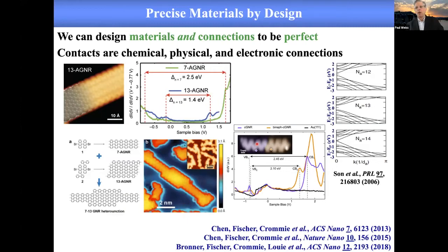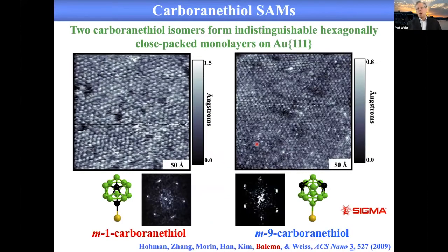Okay, going back to the self-assembled monolayers, those had all kinds of problems because the molecules out of which we assembled them were not rigid structurally. They could conformationally relax, they tilted, and so forth. And so a few years back, we came upon the idea that instead of using flexible chains, if we used rigid cages that stood upright on surfaces, most of the defects in those structures would go away by symmetry. And so we've been working with these upright cage molecules for some time now.